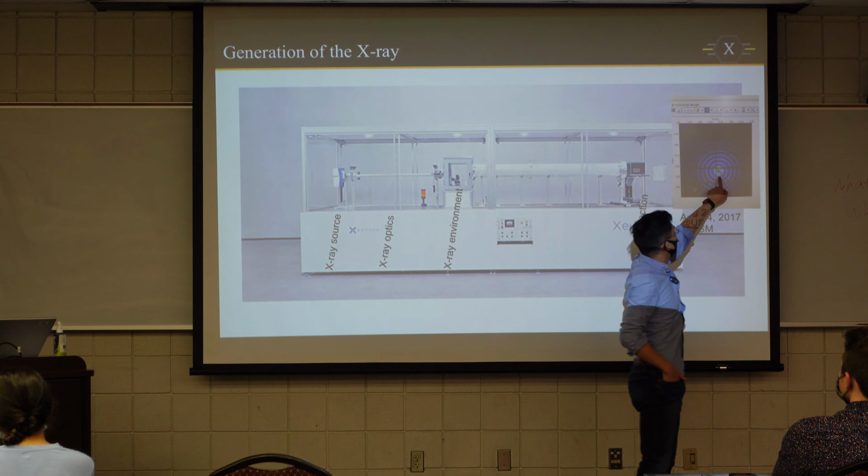If we move the detector a little bit further away, we can probe lower Q region or larger features, but we sacrifice the wider angle. Small angle typically is an SDD of 1.2 meter and above.